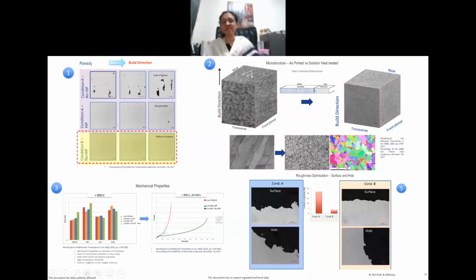So that is what we did in this example I showed you of the power nozzle, which is a hot gas path component operating at temperatures over 900 degrees centigrade. So we tried to optimize the laser parameters for minimum roughness. If you look at the top part here, the surface roughness, you can see from a roughness of 15 to 20 micrometer Ra, we brought it down to 3 to 4. At least on the external surface, it's okay. You can give some grit blasting. You can do some machining.